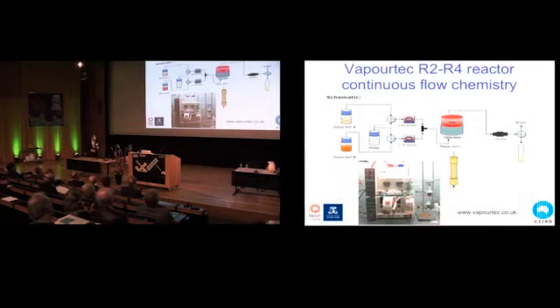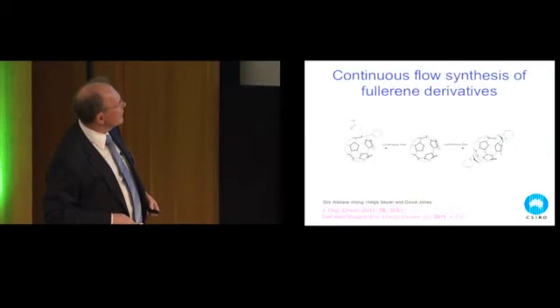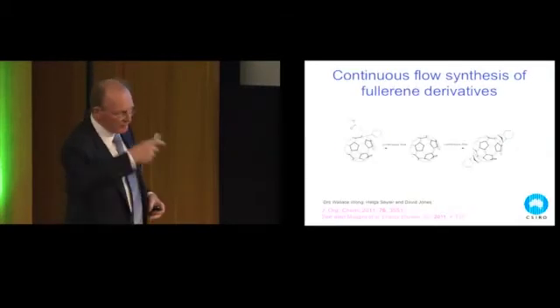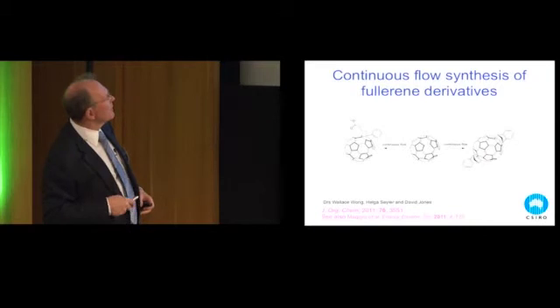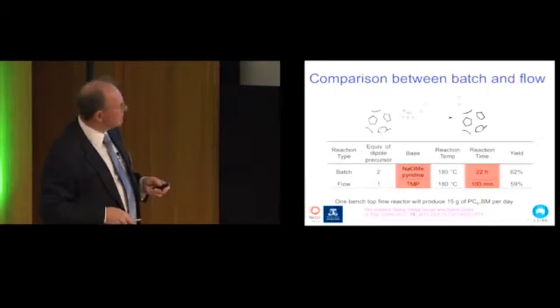So I'm going to skip through this because we're running out of time. But if we're going to print solar cells, we need to make large amounts. And so we're making large amounts by continuous flow chemistry. And this is called a Vapourtec. And we can run this for 24 hours, continuously making, for example, the fullerenes that we use. Here are the fullerenes. This is PCBM. This is another fullerene. And we make them by continuous flow.